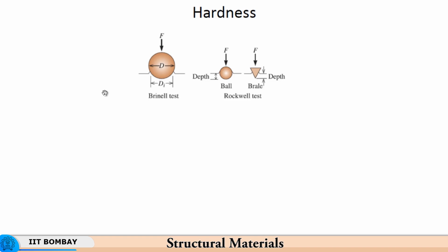So, this is under the Brinell type of test. So, Vickers and Brinell follow this same principle, load divided by the area of indentation, whereas Rockwell follows the principle of measuring the depth. So, you have a ball indenter, it could be a steel ball or anything else, and you can have a diamond indenter depending on the hardness of the material. For example, a ball is used for relatively lower loads, and a diamond is used for relatively harder materials and higher loads. So, the depth of indentation gives you the hardness in the case of the Rockwell test.